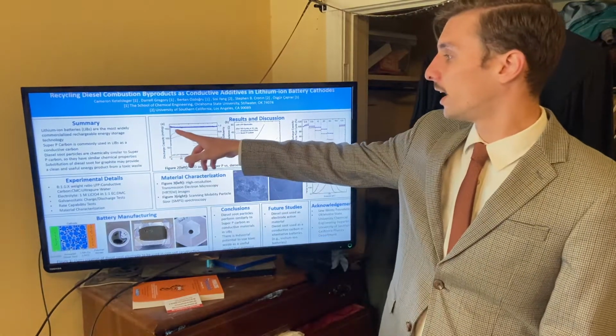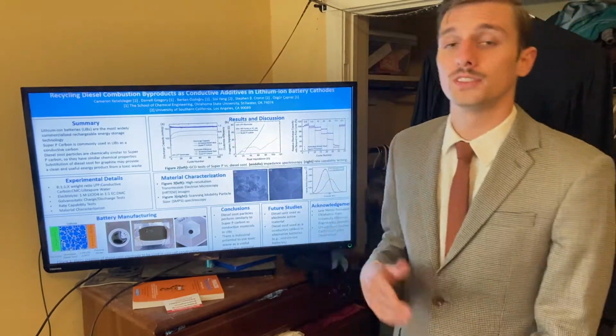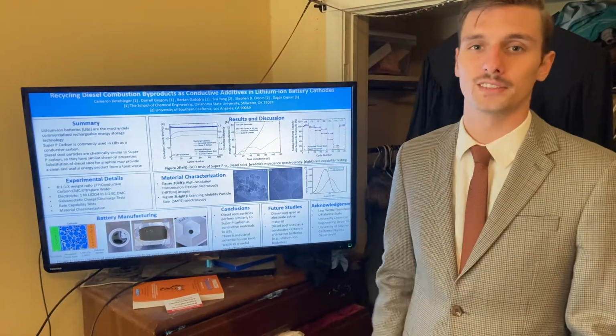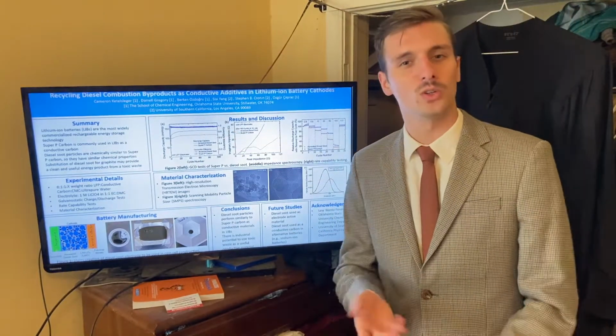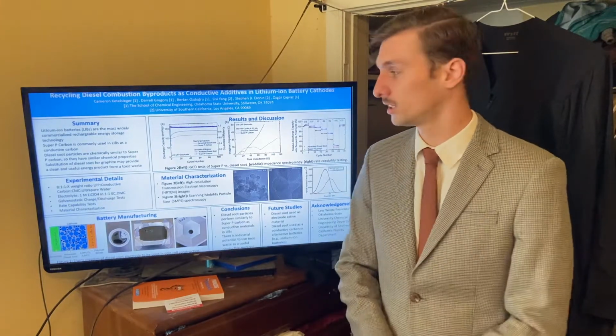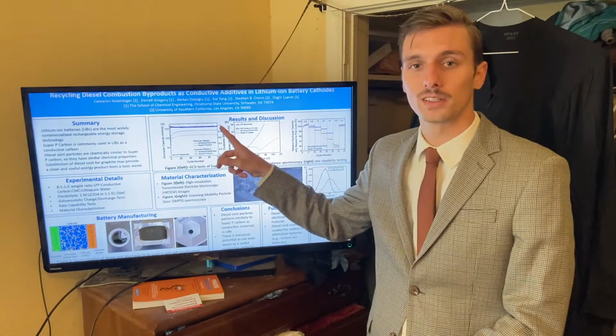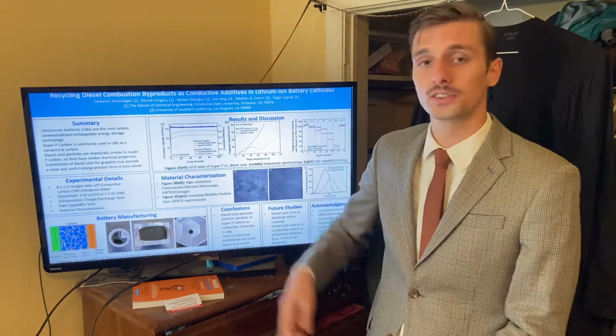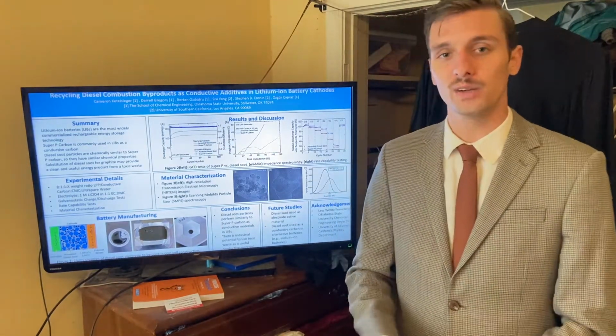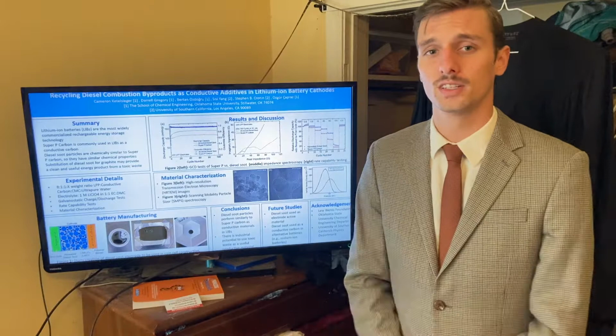Regardless, looking at the Coulombic efficiency, which is the discharge capacity over the charge capacity, essentially how symmetrical is this material charging and discharging, we find 100% for 100 cycles. This means that this material is reliable and can withstand many cycles.